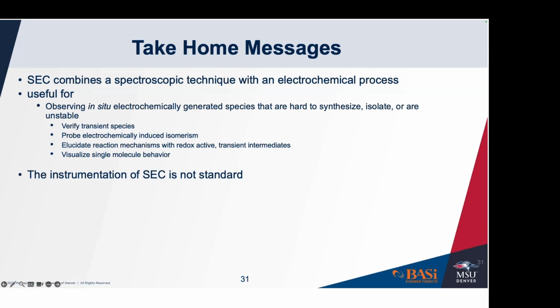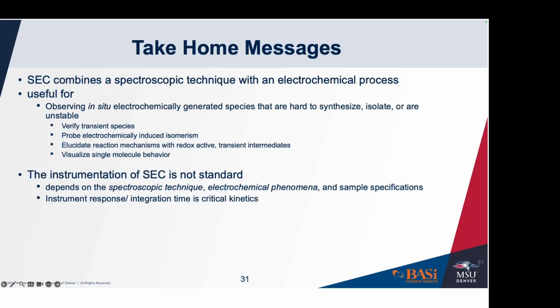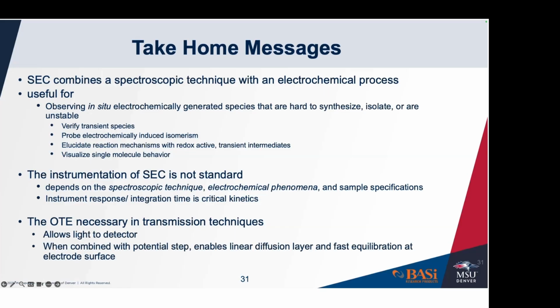However, the instrumentation is not standard. There have been advances in this area, but the instrumentation does depend on the spectroscopic technique and the electrochemical phenomena, as well as the sample specifications that will enable your actual chemical phenomena to occur in solution while doing both the spectroscopy and the electrochemistry. And you need to make sure that your instrument response time and your integration time is appropriate to actually capture the kinetics of the process that you're measuring. In transmission techniques, the OTE, the optically transparent electrode, is necessary so that you can actually detect the light that is being transmitted through the solution. And it is an example of the way that cell design impacts how we can apply these to different types of spectral and electrochemical techniques.